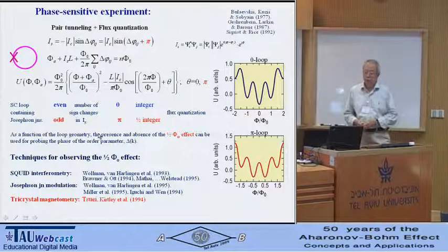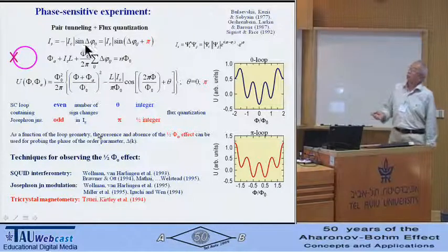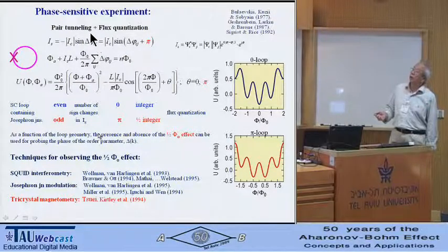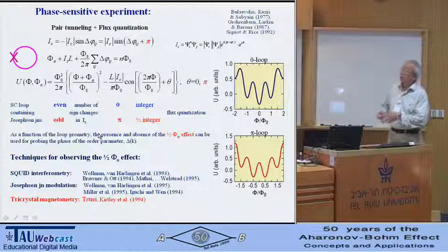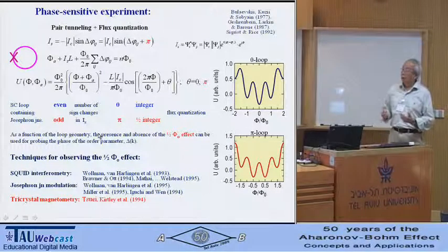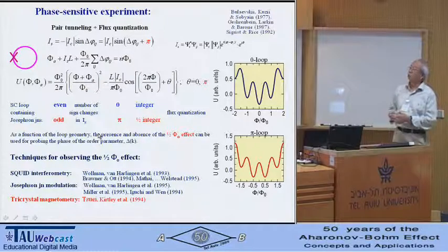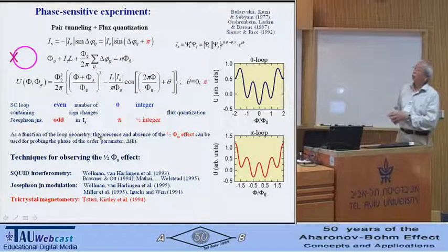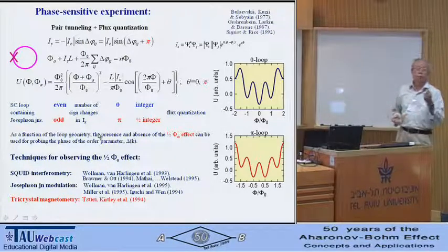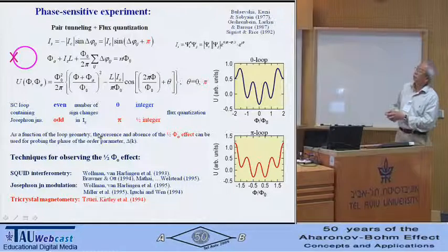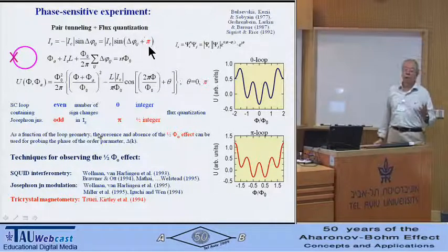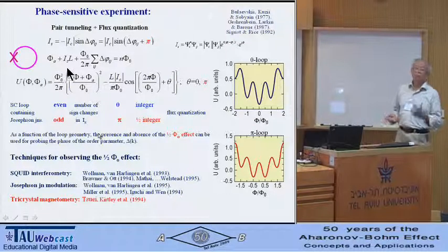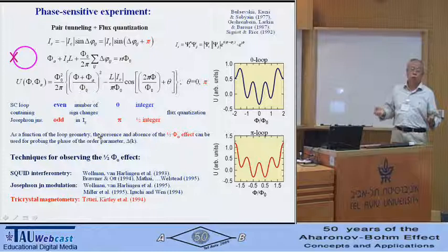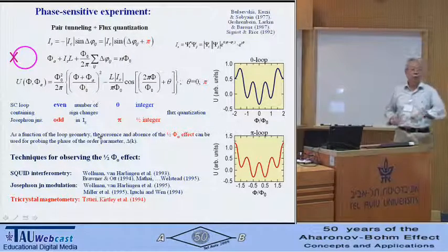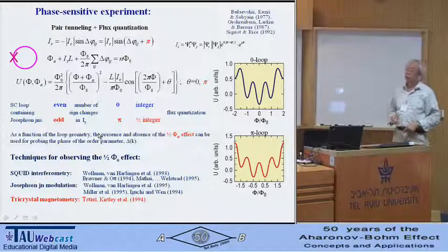Well, a phase-sensitive experiment is based on two macroscopic quantum phenomena, namely Josephson pair tunneling and flux quantization. Here's Josephson's expression for supercurrent. If you make a junction out of an unconventional superconductor, namely a non-S-wave superconductor, then it is possible to have a junction that gives you a negative supercurrent. What that means is, if you absorb this negative sign in the sine function, that will give you a pi phase shift. Now flux quantization is nothing more than the requirement of a macroscopic pair wave function to be single valued as you go around a loop of 2 pi.